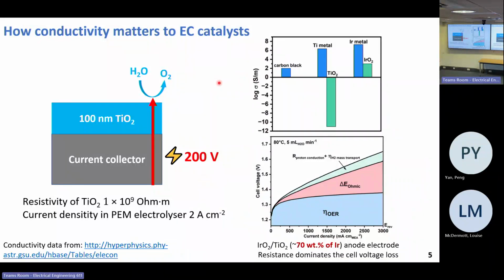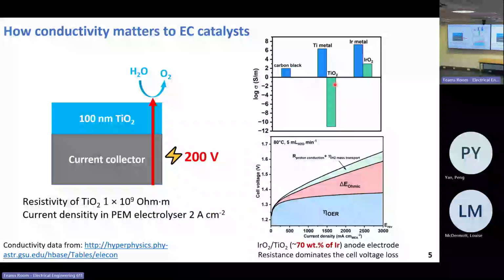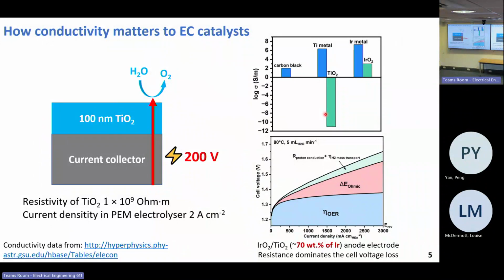Titanium dioxide is very stable, but it's roughly 20 orders of magnitude less conductive than titanium metal when fully oxidized. But iridium is still very conductive when oxidized.